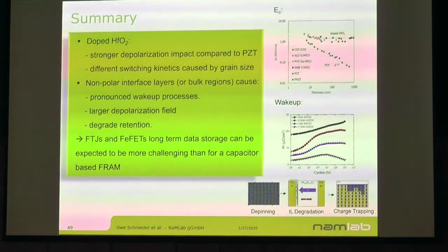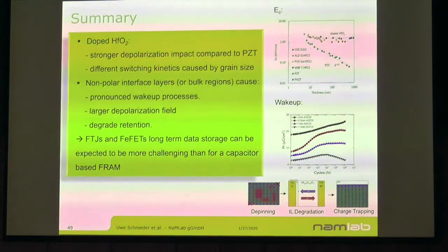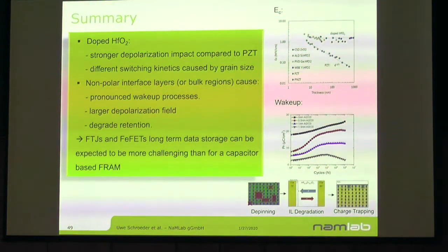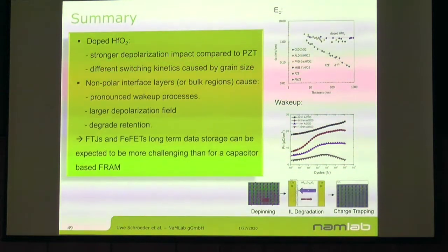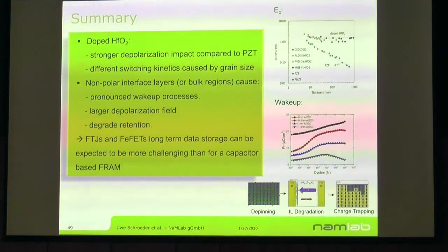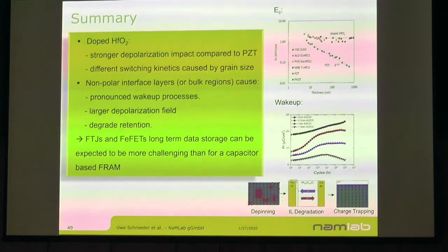If you look at most of the studies currently in literature, it looks like single grains are switching, but since you can't look at this small scale, PFM typically has a 100 to 200 nanometer scale, you see that more and more grains are switching, and it looks like a coalescence of multiple grains rather than domain walls moving over the surface.